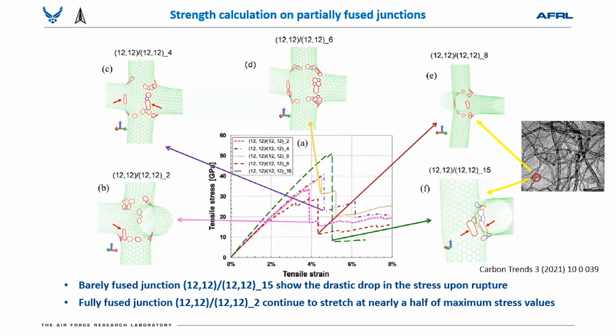That's the idea. So when you want to join the carbon nanotubes next to each other, as I said, all the defects you need to optimize, 7-member, 8-member, or 5-member, and their distribution depends on how they are connected to each other, either fully fused or barely fused. And so we look at all these problems, and with this calculation, we find, as you see, barely fused junction gives you higher strength as compared to fully fused. Although one may assume that, okay, fully fused will be more robust.